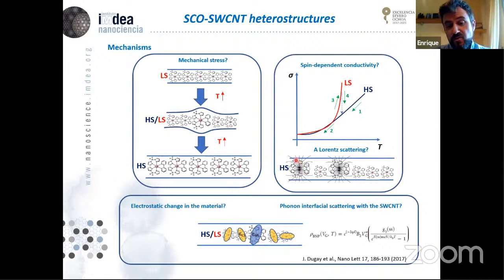It could be as well a magnetic origin, because the spin 2 may be inducing some kind of Lorentz scattering on the tube that we don't have with the spin 0. We don't know, but we don't think this is the case. And also it could be an electrostatic origin, because it is also well known that when the molecule changes volume, it is also changing the electron charge distribution in the molecule, so that the effective dipole moment is changing in the molecule. So this could be coupling to the carbon nanotube, for example, through a local gating effect, or through the interaction with the phonons, as they have described for graphene in this paper here.